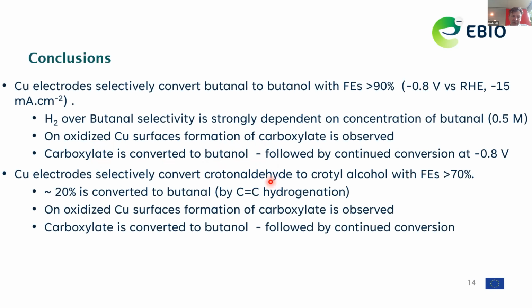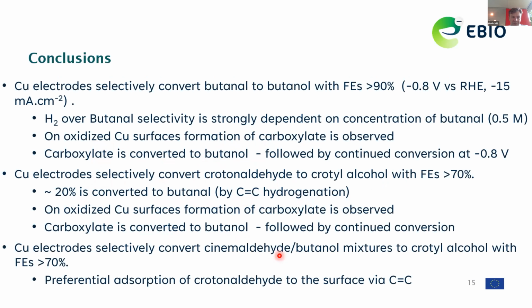For the crotonaldehyde, it's different. It's still very selective to the alcohol. The double bond hardly gets converted, as much as only 20%. On oxidized surfaces, we see the same thing, carboxylates formed, and these are then also converted to the alcohol. And that goes really nicely. And finally, if you have a mixture of the two, it's very selective. Sorry, this should be crotonaldehyde. And not so much to the butyraldehyde in conversion.